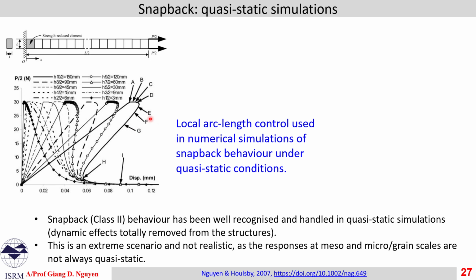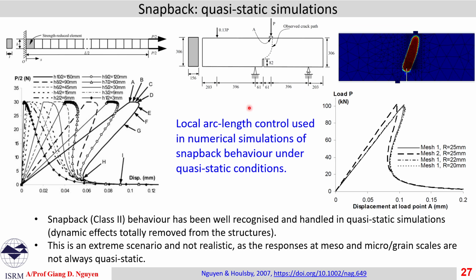And snapback in this case can be captured quite straightforwardly under quasi-static condition. That means our governing equation in this case doesn't include the dynamics effect. It doesn't have acceleration. We remove the acceleration totally from the governing equation and solve the quasi-static equation, and that will require arc-length control to capture snapback. For the structural problem that you can see here, using arc-length control, we can capture quite well the snapback behavior.